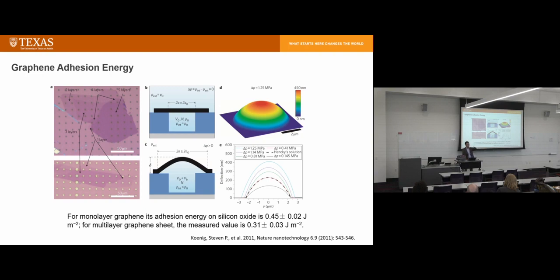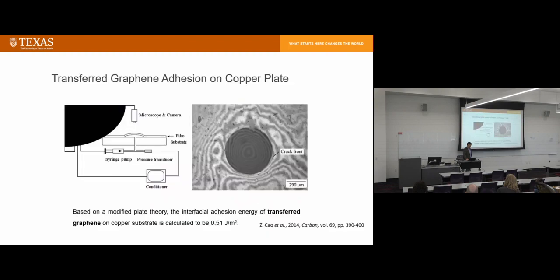So keep in mind this is transferred graphene. You have to grow graphene and then transfer, lay it down onto the silicon wafer, and then measure the adhesive energy between silicon wafer and graphene. The reported value is 0.45 for monolayer, and for multilayer 0.31 joule per meter square. And another study measured the adhesive energy between transferred graphene and copper. It's one step closer, because they're measuring adhesive energy between graphene and copper. The reported value is 0.51. And this is the typical blister test.